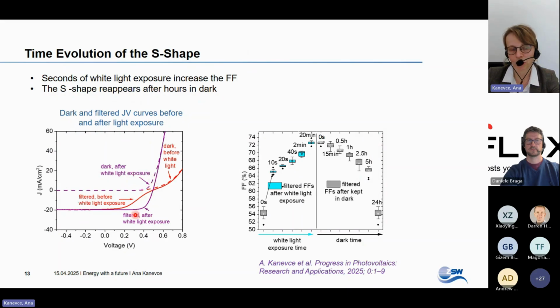The JV curve looks as it should, a diode curve, exponential. Also, in the dark curves, the turn-on voltage is lower. Now here, I try to look at the time evolution of this S-shaped curve, and one sees that after seconds of white light exposure, the fill factor jumps significantly. And then it improves and improves and saturates after minutes. The phenomenon is reversible, and then after hours, the S-shaped curve and the fill factor loss come back.